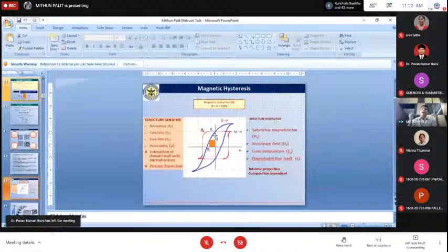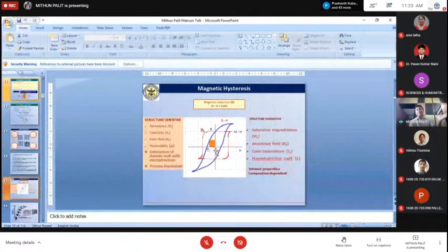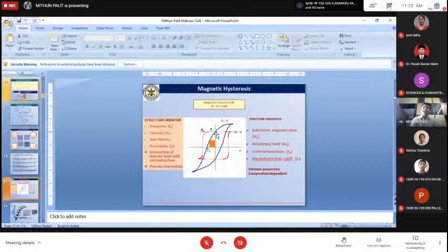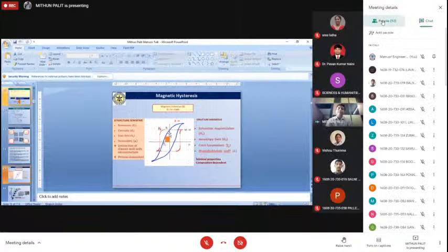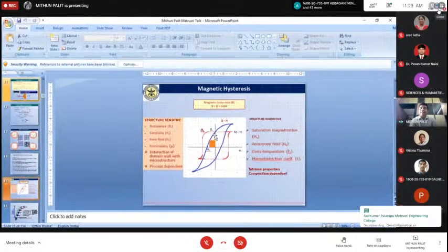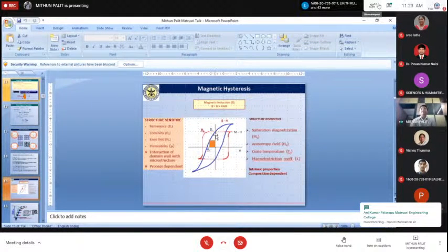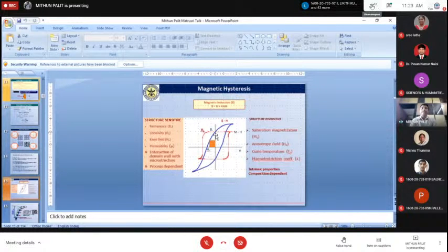And to nullify the remnant magnetization, we need to apply some amount of field in the opposite direction. When we apply this much field in the opposite direction, we can actually get rid of this remnant magnetization, and therefore this negative field which is required to nullify the remnant magnetization is called the coercivity of the material. So this is the remnant, that is, at H equal to 0, the value of M is called the remnant magnetization. So at the saturation magnetization, and the negative field required to nullify remnant magnetization is coercivity.